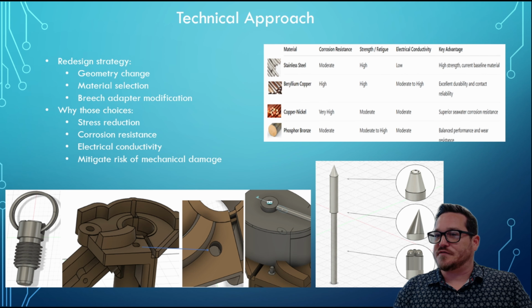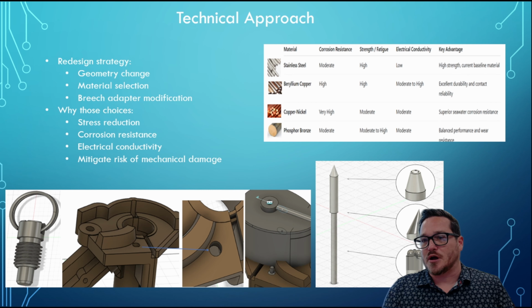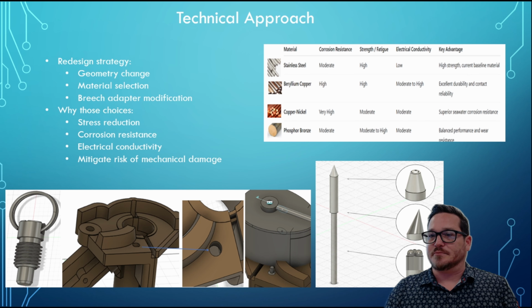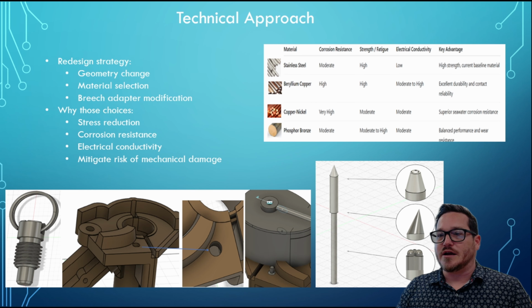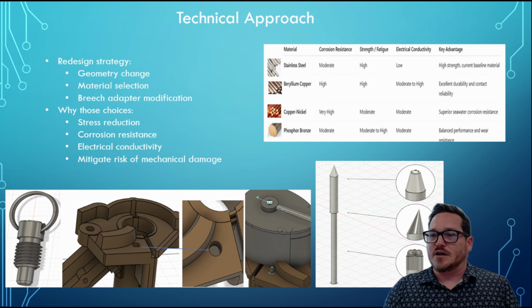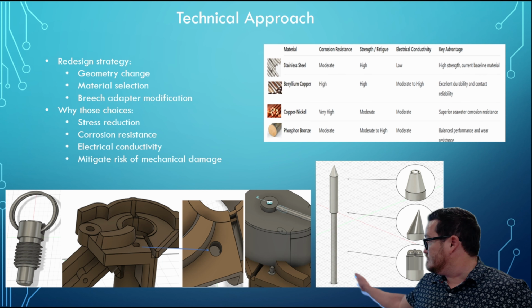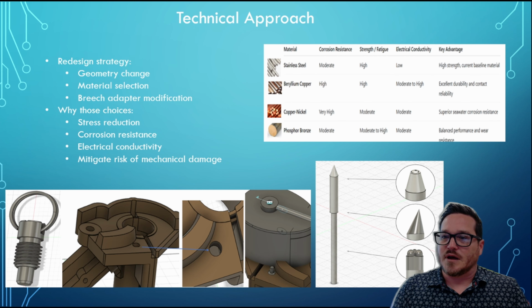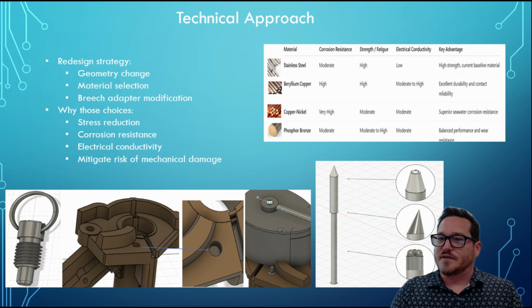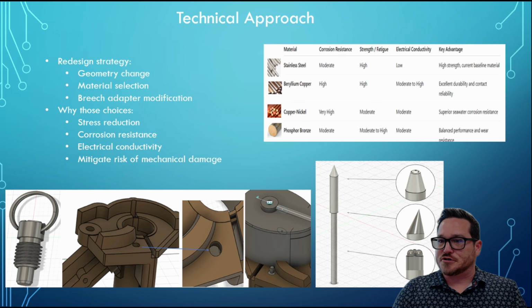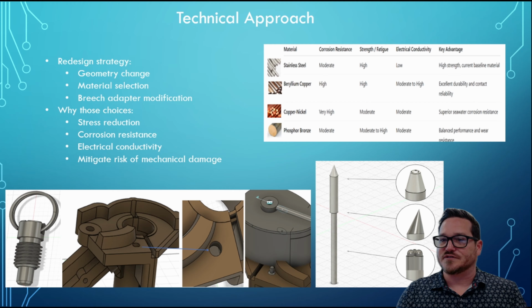My strategy for the technical approach had 3 main parts. The first was altering the geometry of the contact pin tips. In the picture on the lower right, you can see the original pin design. It's on the left side of that picture. It comes to a very fine and sharp point. This is seemingly to penetrate the contact plates inside the probe canister. My research showed that this is not always the best way to maintain electrical contact between 2 surfaces.